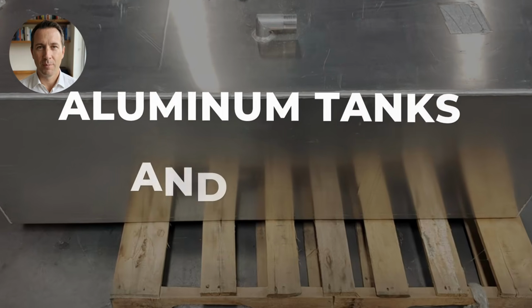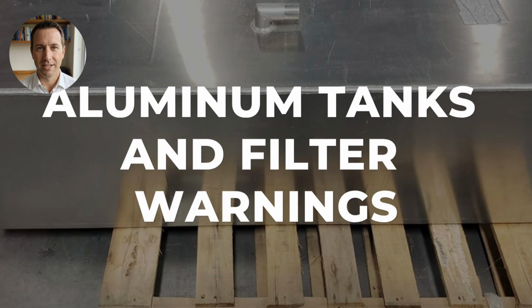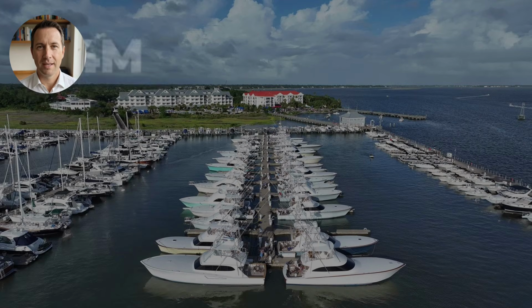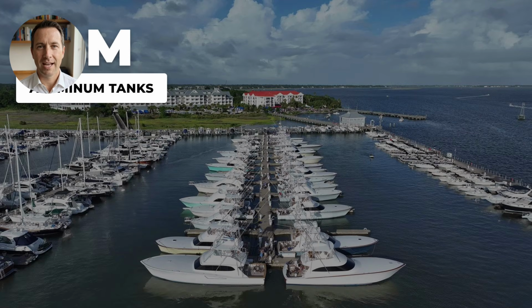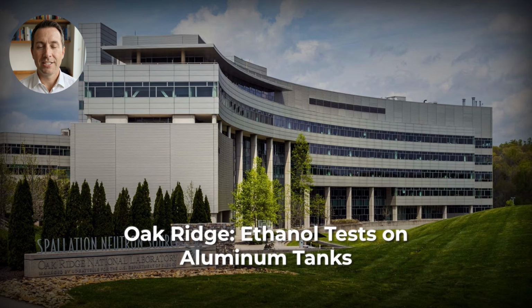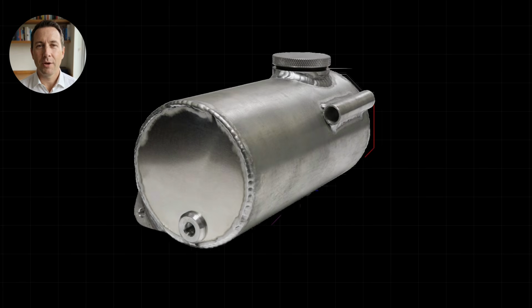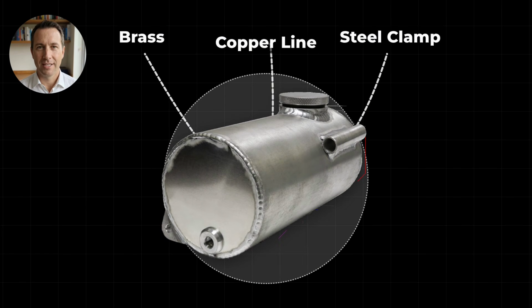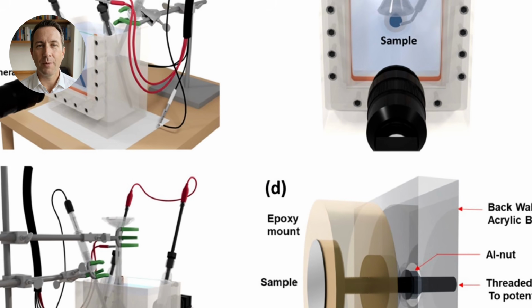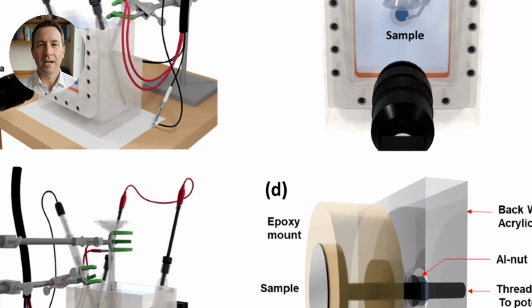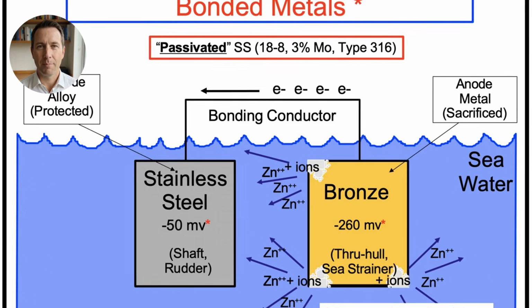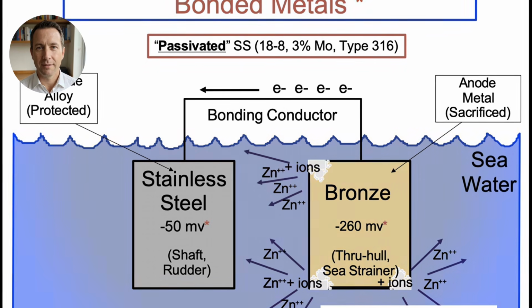Now if you are thinking, well, my boat has an aluminum tank, so I'm safe. You are not. Aluminum suffers a different kind of attack, and about 4 million boats in the US have aluminum fuel tanks. Oak Ridge National Laboratory tested this extensively. Ethanol degrades the aluminum oxide layer that naturally protects the metal surface. Once that barrier is compromised, the raw aluminum underneath oxidizes rapidly, but the bigger threat is galvanic corrosion.